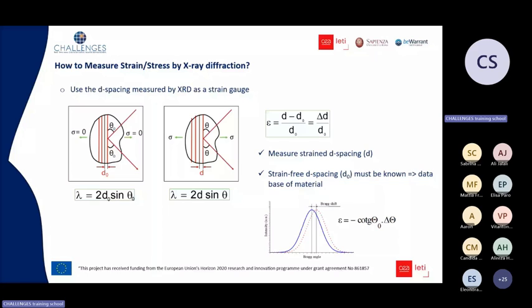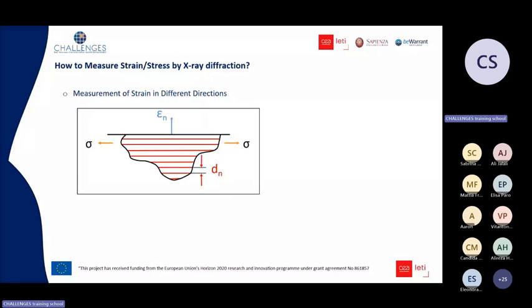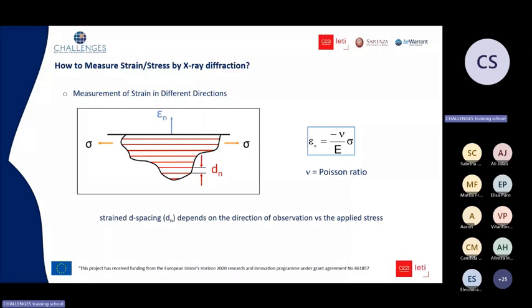What is interesting to note is that if you look at the strain in different directions, you have different behavior. For instance, if you apply the stress parallel to the lattice planes, you will have an extension of the distance in the direction of the stress, but perpendicular to this applied stress, you will have a retraction of the lattice spacing. It can be written through this equation where the strain along the direction normal to the lattice plane is equal to minus nu divided by the Young modulus multiplied by the stress. This coefficient is the Poisson ratio, which gives the relationship between the applied stress and the strain perpendicular to the stress. So what is noted here is that the strain d-spacing depends on the direction of observation versus the applied stress on the material.